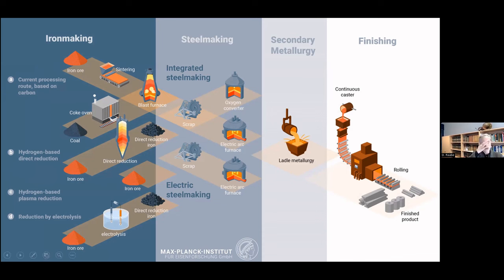But it's interesting because all this reductant material, the fossil carbon is a reductant, is also partitioned into the iron. So you don't produce iron in a blast furnace. You produce an alloy of iron very high in carbon that you again have to render devoid of the carbon downstream. So you put a lot of reductant in, which you later take out. So all this makes it a very, very dirty process.